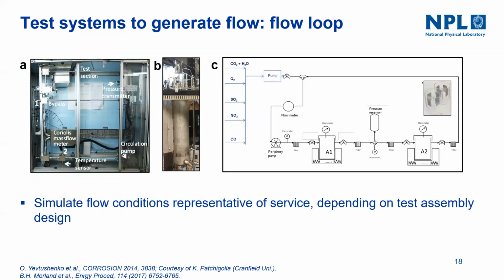So another ideal system is the flow loops. So this can be representative of service depending on the test design. So if you have a pipeline kind of loop and having the specimen in the pipeline shape, you can generate flow conditions similar to that. So there are different types of flow loops in the literature, but actually more unique autoclave flow loops can be designed.